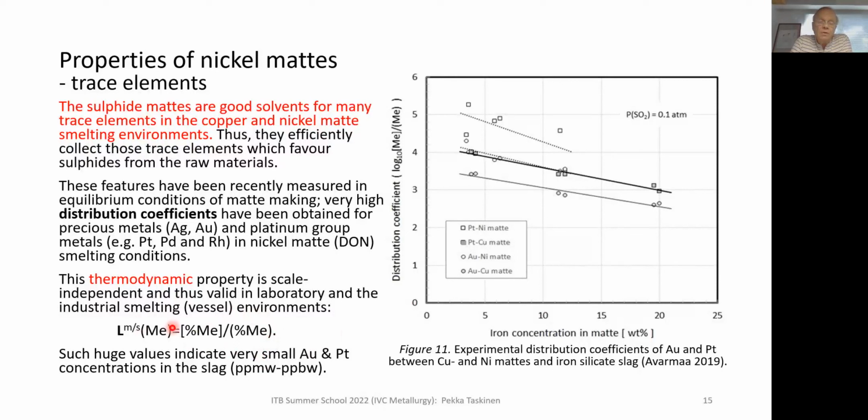And because this is a value without any scaling factor, these distribution coefficients are valid in laboratory, but they are also valid in large-scale furnaces.